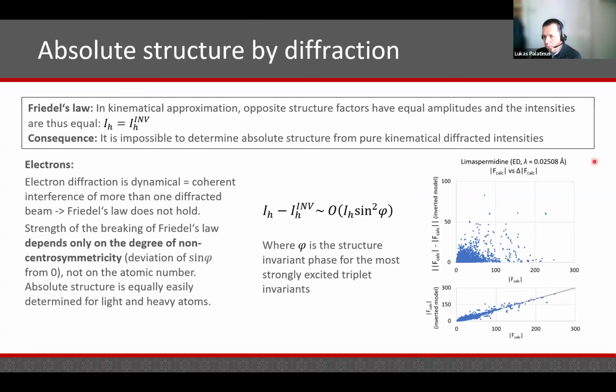So if you recall this plot for X-rays, the scale here was around 0.1, 0.2, for the scale in hundreds on the horizontal axis. And here, on about the same horizontal axis, we have differences that reach up to 50 or even more. So the effect is of essentially the same order of magnitude, or at most one order of magnitude less than the actual amplitudes. And that's why it is much easier to determine absolute structure from electron diffraction than from X-rays.